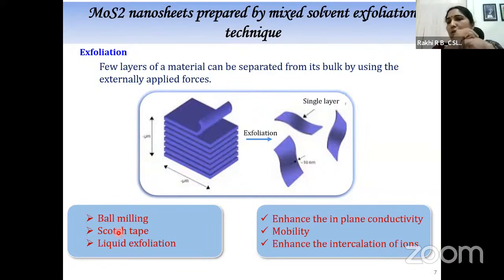Now, MoS2 can be prepared by different methods, either by a top-down approach or a bottom-up approach. Top-down approach means we take the bulk MoS2. We can commercially purchase bulk, multi-layer MoS2. Then by chemical exfoliation, the scotch tape method or ball milling, we can separate the individual layers. By scotch tape, we can separate a single layer, but by sonication we can separate out few-layer MoS2, like few-layer graphene. So that is one approach.